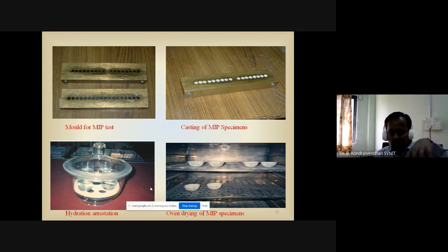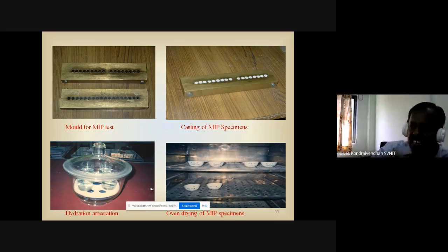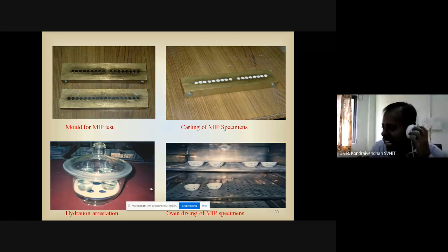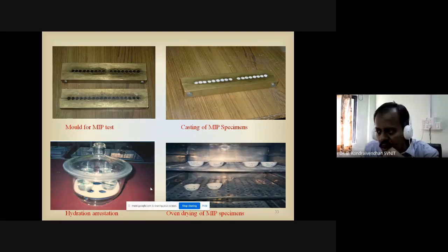How to do it? There is a procedure. You have to keep the samples inside isopropyl alcohol in a beaker. Then the beaker of isopropyl alcohol should be kept inside the desiccator, which will maintain the relative humidity. You keep the sample for 10 days. During the 10-day period, the isopropyl alcohol enters the sample and replaces the pore water.